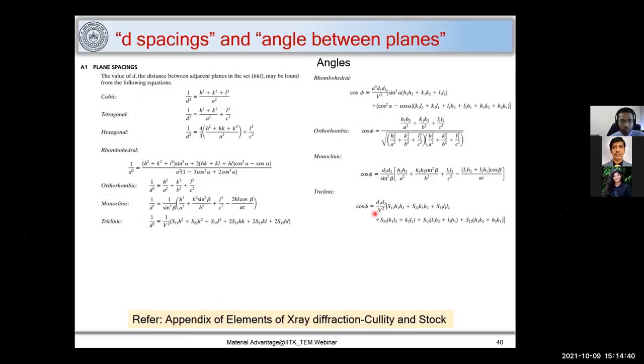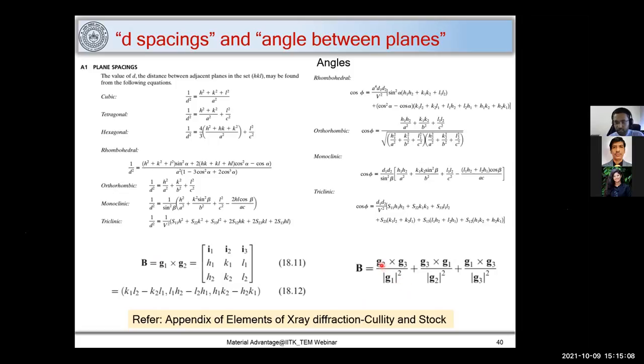This is a tedious job, but if the pattern is unknown to you, you have to do these calculations, find cos phi and D, and iterate to find the final D and cos phi. Once you get that, you take a cross product to find the zone axis. If you have these two G vectors, you do a cross product of them and find the zone axis. If you know three vectors, G1, G2 and G3, you can find the zone axis from this relation. This is already mentioned in Carter's book; you can read about it. So this is a general methodology to index any diffraction pattern for any crystal structure.